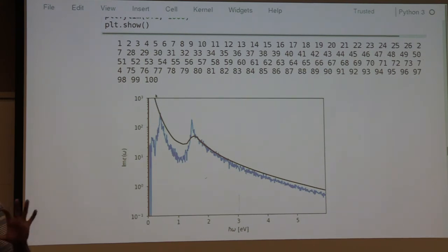So the phonon assisted optical transition that I'd mentioned in the slides, but which we have not calculated here, is responsible for most of this remainder. Right? So in the results I showed you yesterday, by adding that process, that worked out quite well. But that still doesn't explain how I can have this peak that goes above the experimental results here.